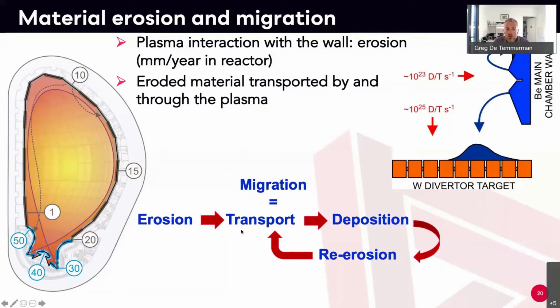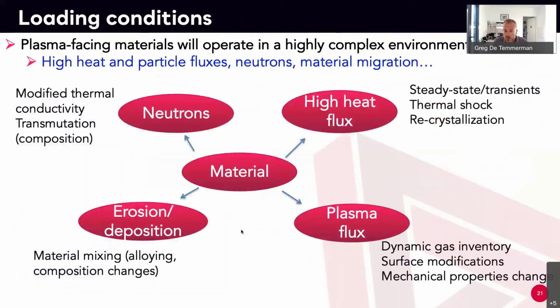a continuous cycle. So if I look at the conditions the material has to face in the fusion reactors, I have 4 components. I have the high energy neutrons. The neutrons in the fusion reactors will typically be at the 14 MeV energy, which is 10 times higher than energy in a fission reactor. So we have a lot of neutrons, we have high fluxes, but they are extremely energetic, which is creating a lot of transmutation. It's creating hydrogen and helium in the material. It's modifying its thermal conductivity.